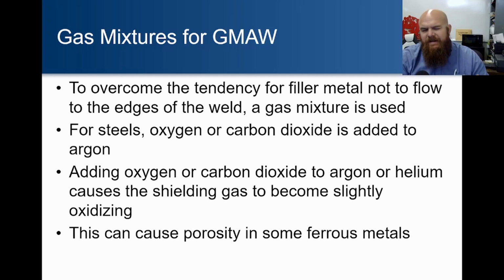Sometimes you'll see oxygen, and even though oxygen is something that causes porosity, it will allow the heat to kind of burn a little bit deeper. And what happens is the argon actually sits lower because it's heavier, and the oxygen's up a little bit higher, so it's not actually getting into your weld. They kind of separate out because of the weight of those things. You do have to worry a little bit about porosity if you have the wrong pressure set up within this stuff.